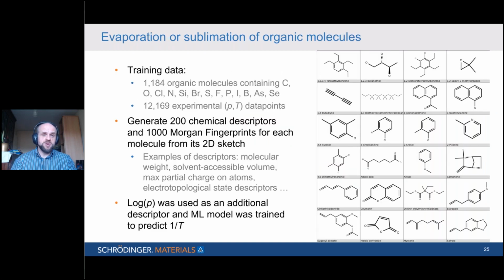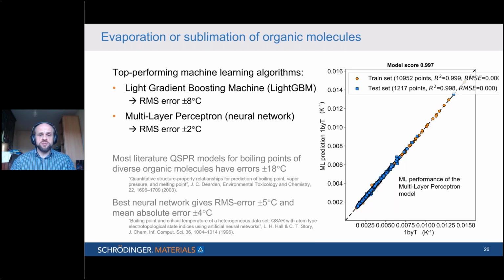We generated it in a very similar way. We actually had an even larger data set here. People have been collecting data on the volatility of organic molecules for a long, long time. And there's some really nice data sets out there. So we had a data set with 12,000 points. And this we were also able to fit against in a very similar way. So I won't go into it in huge detail. You see there the correlation of, again, the predicted temperature against the experimental temperature. And the error here for the neural network that we used is around 2 degrees Celsius.